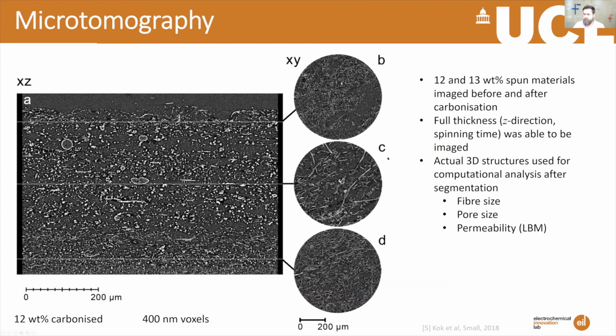This is an example of a tomography slice through the material. You can see there's a wide variety of fiber sizes and void sizes around these fibers as well. And also the material looks quite different if you take cross sections through the different parts of the thickness. Of course, with SEM, you'd only see either one side of this, and so you could miss some of those things.